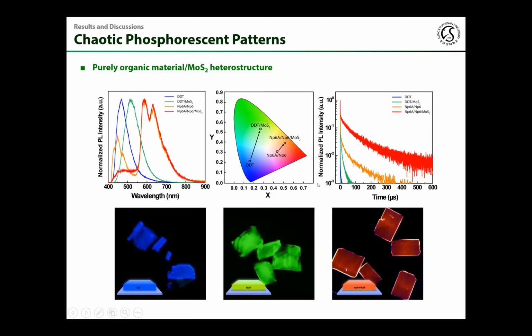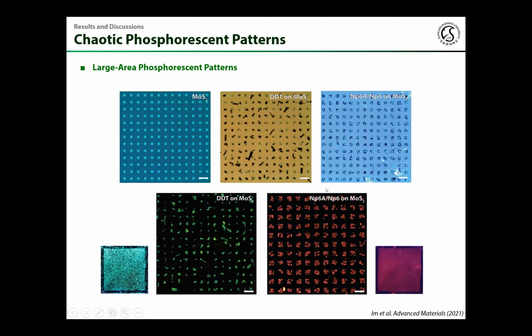In addition, the time-resolved PL spectra also present that DDT and Np6A and Np6 increase their lifetime with MoS2. This result indicates that the MoS2 actually stabilizes the phosphorescence behavior of purely organic materials at room temperature. So, based on this technique, I formed the large-scale phosphorescence pattern for the chaotic PUF.